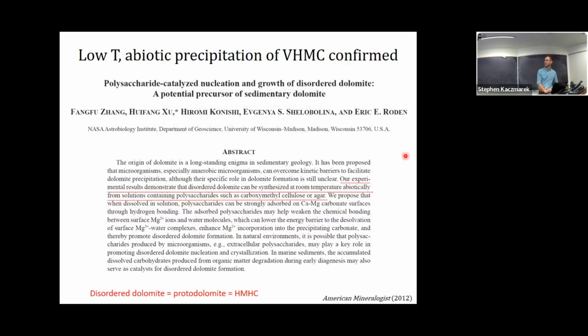More recently, that same paper showed that you could make this disordered dolomite phase at low temperature just using some carbohydrates, some polysaccharides. You don't need any active microbial metabolism going on either. So the model here, the microbial dolomite model, that we're somehow using microbes to change the kinetics and change the chemical system, is on kind of shaky footing now, because not all the experiments have produced this ordered dolomite, and subsequent experiments show that it's pretty easy to make this disordered phase that we see in the experiments.